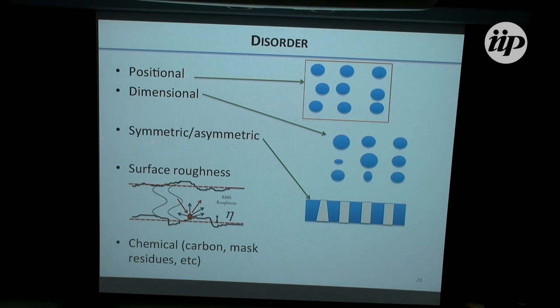There's another disorder type which has to do with symmetric or asymmetric structures. So you could make cones that are upside down. You could make holes that are perfectly rectangular, some which have this conical shape or inverted of that. All that is going to contribute to the band structure of the phononic crystal. And then you have the much vilified surface roughness. The surface roughness picture that we take from SEM looks something like this. There are some atomic steps, some little holes, and you describe these by a particular size, and one thinks of it as a random roughness, and one that can produce a specular reflection or be highly dissipative and change not only your phase but also your amplitude.